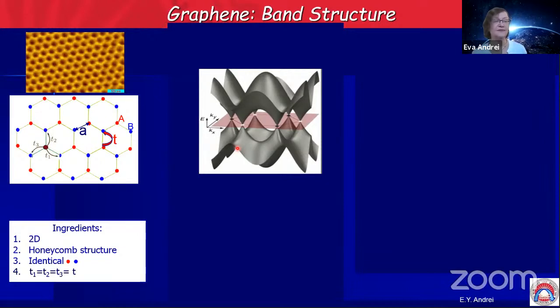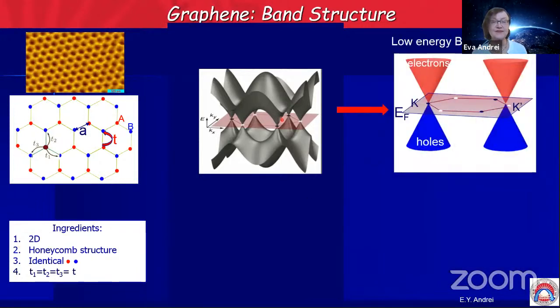One thing to point out here: if you look at the ingredients, none of them requires it to be carbon. In fact, if you put together these ingredients, you can create this strange band structure with almost anything. So people have done it with cold atoms. They've done it by taking carbon monoxide and arranging it in a honeycomb structure on top of copper with microwaves. They've also done it with atoms that are not carbon, atoms along the entire 4th column in the periodic table. So these conditions are purely geometrical. So let's zoom into this.